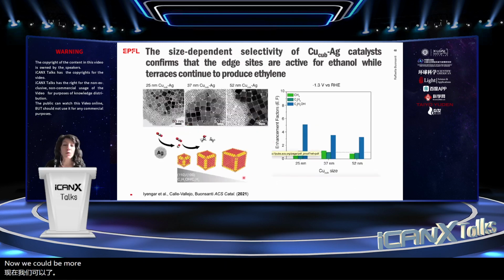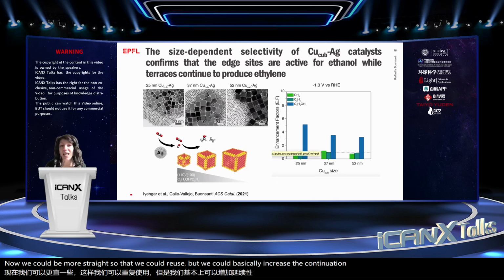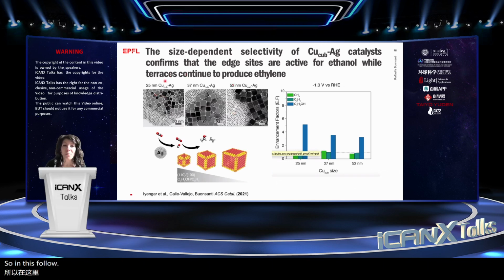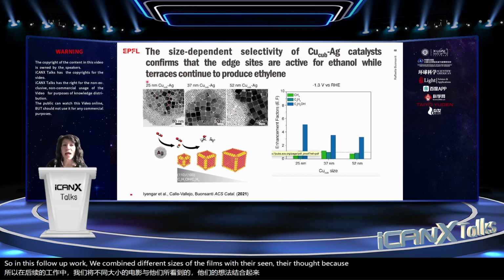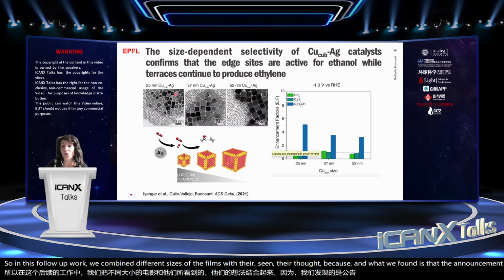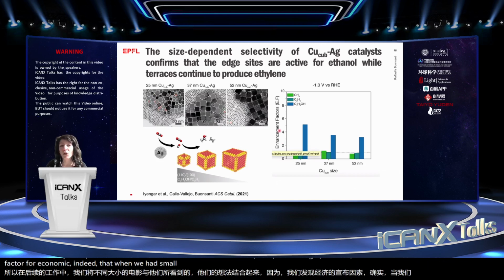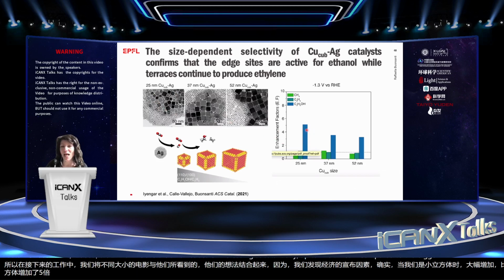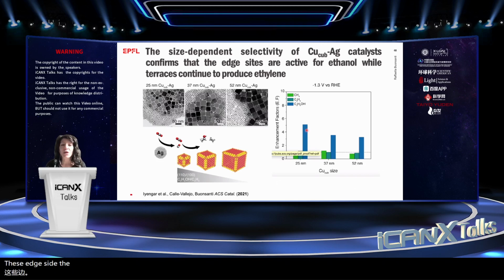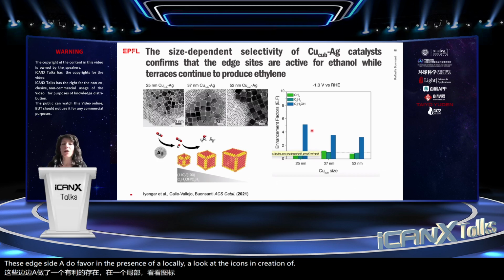Now, we could demonstrate that we could basically increase the contribution of the edges by making copper cubes smaller. So in this follow-up work, we combined different sizes of the cubes with the silver particles. And what we found is that the enhancement factor for ethanol, indeed, when we have small cubes, increases substantially, up to 5 times compared to the bigger sizes, because indeed these edge sites do favor, in the presence of a locally high concentration of CO, the CO-CH coupling.